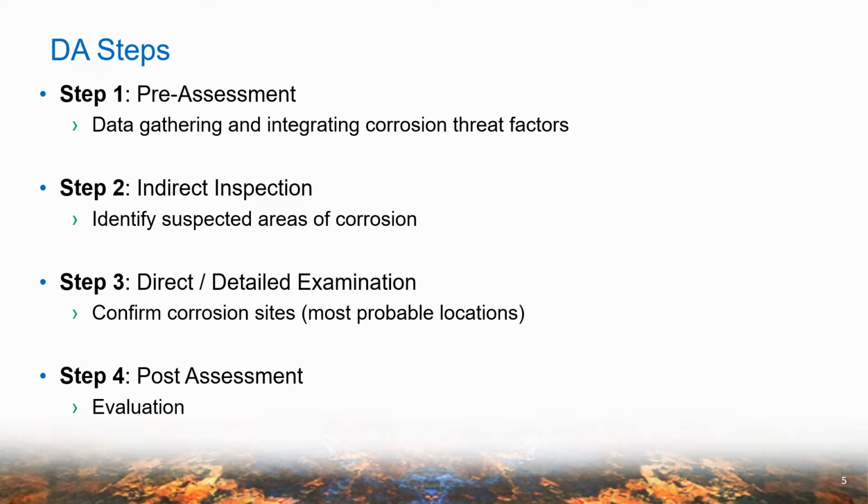For the ICDA, that is when you are going to define the internal corrosion predictive modeling that you're going to use for the assessment. Step two, for the ECDA and stress corrosion cracking direct assessment, is when you have to work on the pipeline to capture cathodic protection information, pipeline elevation information, the coating, soil, everything you can use to predict the likelihood of external corrosion for the ECDA.